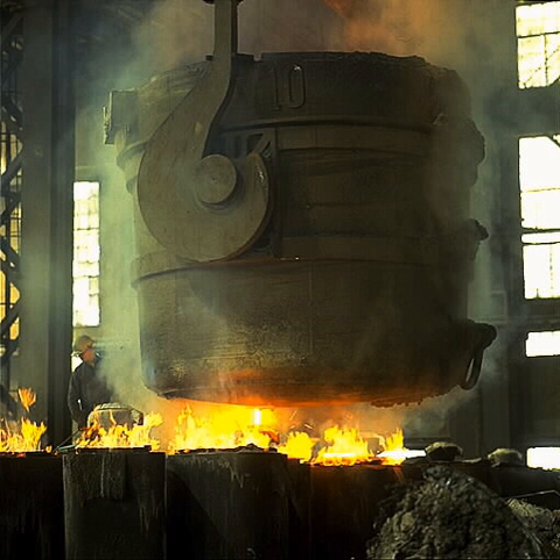Tiny amounts of 0.02 to 0.1% magnesium, and only 0.02 to 0.04% cerium added to these alloys slow the growth of graphite precipitates by bonding to the edges of the graphite planes. Along with careful control of other elements and timing, this allows the carbon to separate as spheroidal particles as the material solidifies. The properties are similar to malleable iron, but parts can be cast with larger sections.